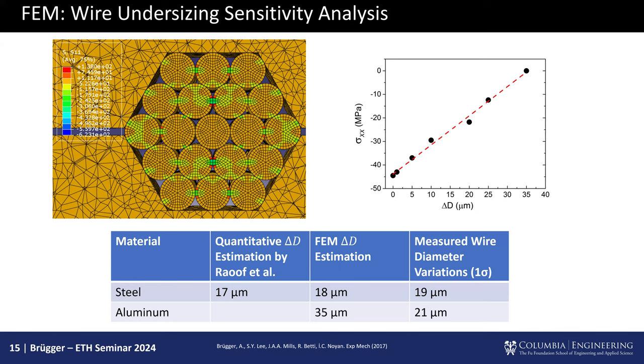We can posit relatively confidently that imperfect diameters are probably causing this chaotic behavior. The wires undulate in diameter along their length due to poor zinc coating — the intermetallics cause diameter variations. Even more disturbing is a monotonic increase in diameter, a non-stationary stochastic process: as wires are cold drawn through a die, that die wears. So the wire starts small and a kilometer later it's larger. That means you have reliably small wires and reliably large wires along the cable length, which means if a small wire breaks, you're in trouble.